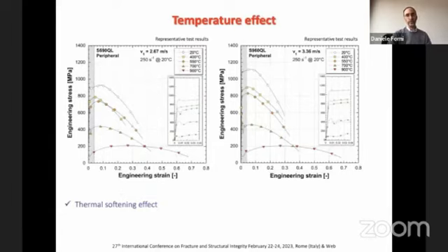So something about the temperature effect. It's obvious, we know, that at increasing temperature, we have a decrease in the mechanical strength. But we have observed in particular that up to 400 and 550, so the yellow and the orange curves, we have only a limited decrease in strength. While for higher temperature, let me say starting from 700 Celsius, the decrease is more evident, and also the total elongation, as you can see on the red curves.